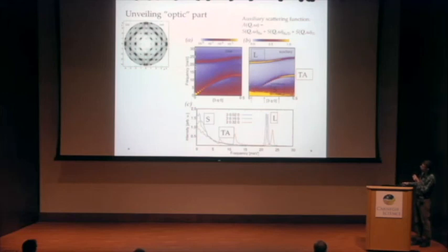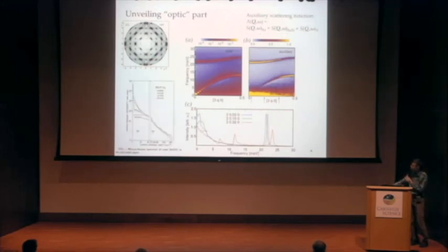And close to the zone center, you get this kind of spectrum. So this is from the Slater mode, the titanium motion. There's the acoustic branch here, and there's the motion of the barium. And the characteristic frequency of that mode corresponds to one which is measured, let's say, in infrared or hyper-Raman spectroscopy. So we know that this mode is really the soft mode which describes the dielectric constant of cubic barium titanate.